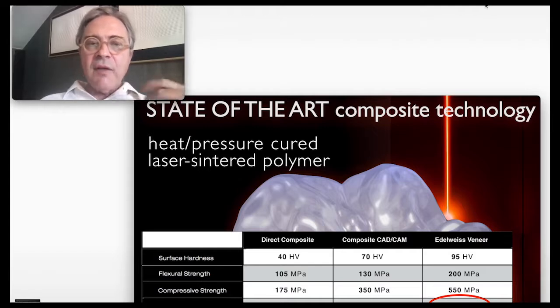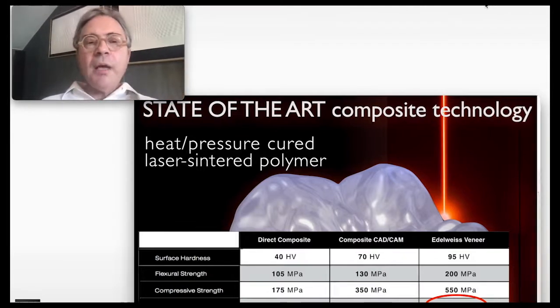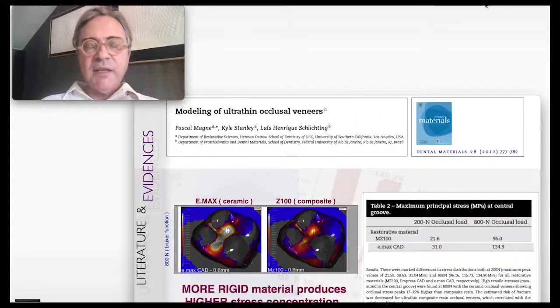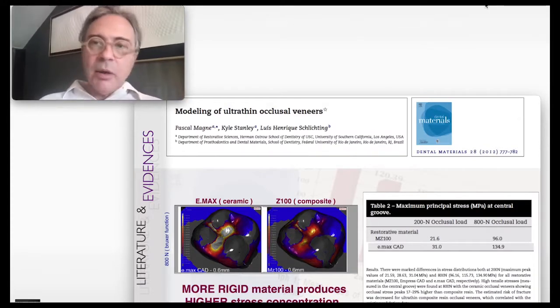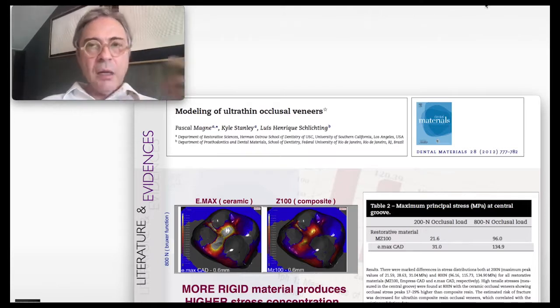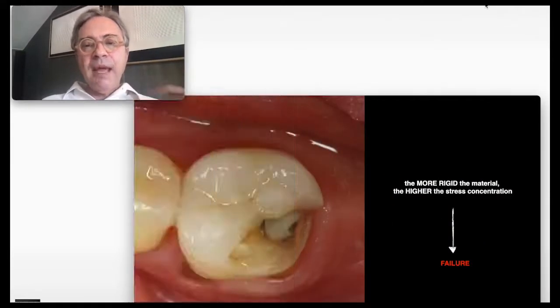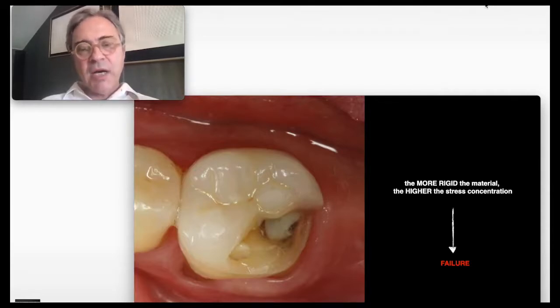And this combination of high strength but low flexural modulus is critical for successful restoration with occlusal veneer, especially in heavy grinder and bruxer patients, because it produces optimal biomechanics and reduces the risk of chipping and fracturing. We know from laboratory research that occlusal veneers fabricated with a hard and rigid ceramic produce much higher stress concentration upon loading than the same occlusal veneer fabricated with a less rigid composite material. And the more rigid the material, the higher the stress concentration and the risk of failure, especially in heavy grinder